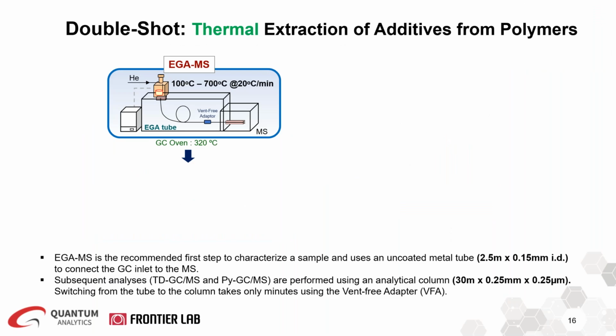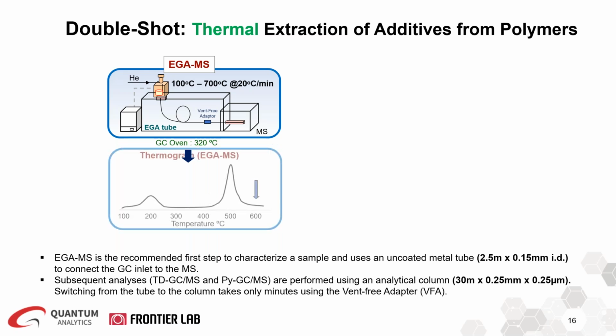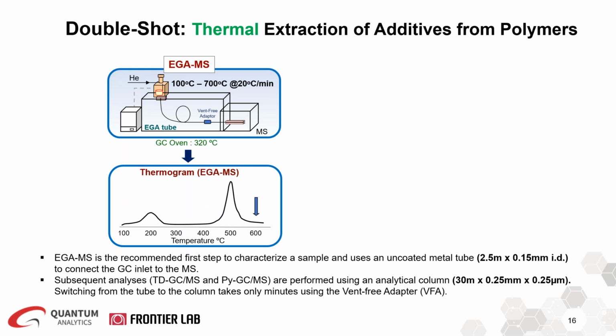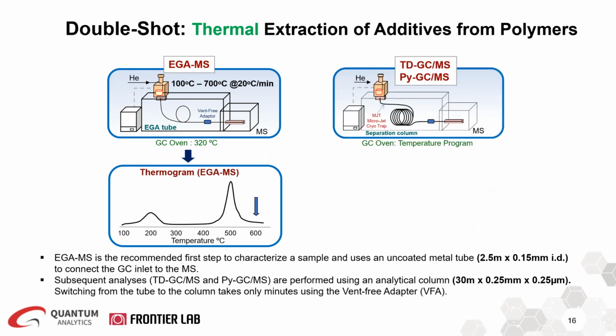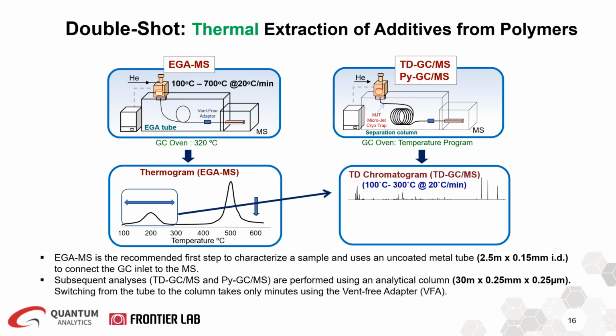This is the double shot analysis, which is the thermal extraction of additives and volatiles from the polymer. First, the EGA is performed, in this case 100 to 700 degrees at 20 degrees per minute, and as shown here, the EGA thermogram is obtained. To further analyze the peaks from the EGA, the tube is then switched to a separation column using the vent-free GCMS adapter. Then the furnace is programmed from 100 to 300 C, 20 degrees per minute, to obtain a thermal desorption GCMS chromatogram